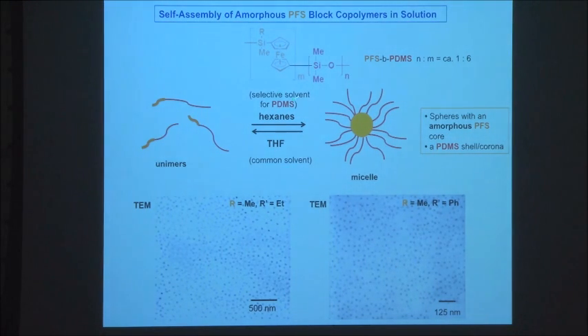If you then add slowly hexanes, which is a selective solvent for polydimethyl siloxane, you'll get micelles where the PFS block will form the core. And in this case, with the case of methyl ethyl or methyl phenyl, you can look at the structures that you form in solution. You can do this by a number of methods. Here's transmission electron microscopy after solvent evaporation, and you get spherical micelles. And this is exactly what you'd expect based on the behavior of organic block copolymers where the core is amorphous.